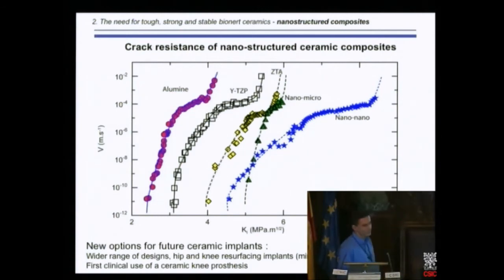Here is V versus K1 curves. I've bored you with this V versus K1 curve today, but that's important for implants especially. This is alumina, YTZP, so current solution in orthopedics, I think also in dental field. This is conventional ZTA, and this is the nanomicro and the nanocomposites. So with both, we have a strong increase of the threshold. So we have now clearly new options for future ceramic implants.